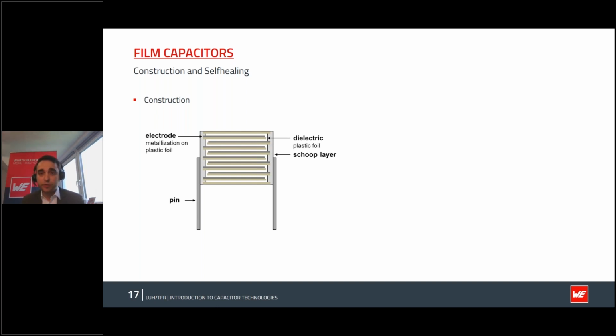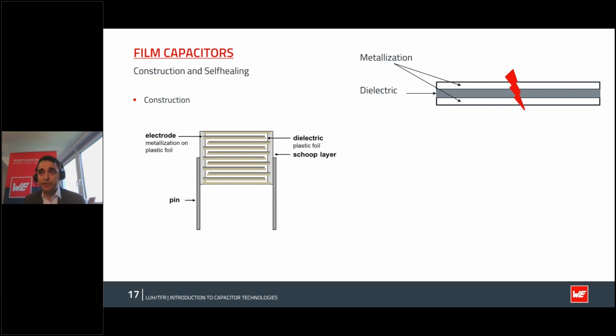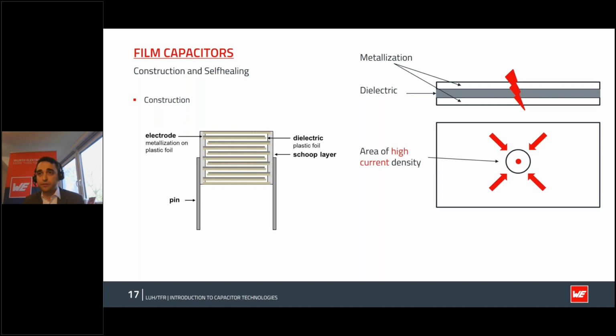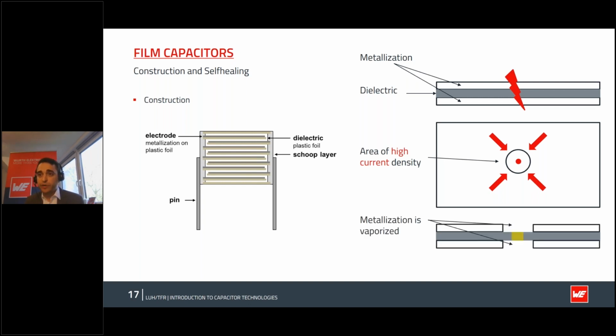This internal structure has self-healing properties. So you'll have the metallization on both sides of the dielectric as it's rolled up. And whenever there's a failure mode, usually penetrating the dielectric, you'll have an area with a short circuit, and it's an area with a high current density. So very much current on a very small area, this generates heat. In fact, it generates so much heat that it will actually vaporize the metallization and even the dielectric in some cases, and then it can generate a plasma to further pull them apart. So the surface area will decrease, but the capacitor will still work as a capacitor at a cost of a small loss of capacitance.